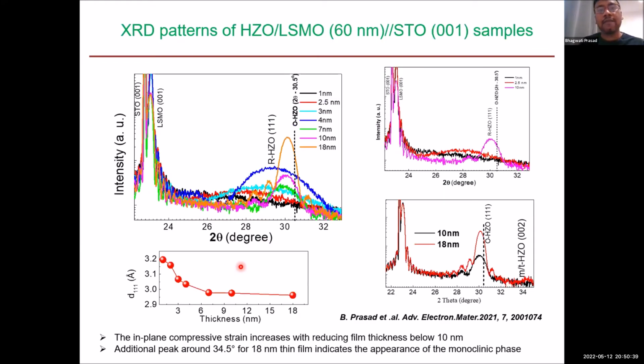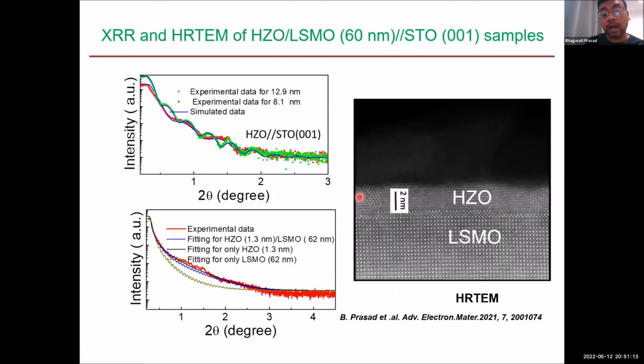So we have also tried something in this space. What we have done is that we have grown the HZO, zirconia-doped hafnium oxide, on an LSMO bottom electrode with an STO substrate by pulsed laser deposition techniques. You can see the films that we grew, all the way from 18 nanometers to 1 nanometer. When you reduce the film thickness below 10 nanometers, it becomes a rhombohedral phase. This is all XRD quality data.